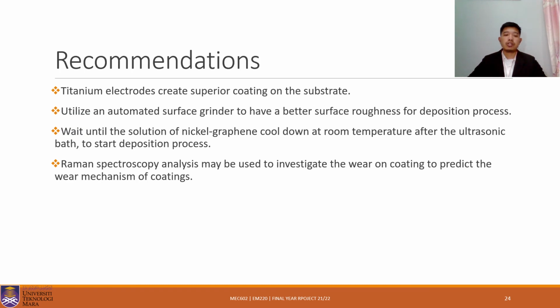For the recommendation, 1. We can use titanium electrode to create superior coating on the substrate. 2. Utilize an automated surface grinder to have a better surface roughness for deposition process. And 3. Wait until the solution of nickel graphene cools down to room temperature after the ultrasonic bath to start the deposition process. Lastly, Raman spectroscopy analysis may be used to investigate the wear on coating to predict the wear mechanism of coating.